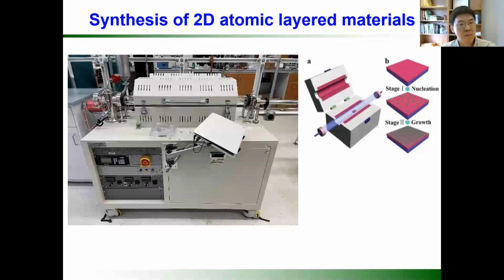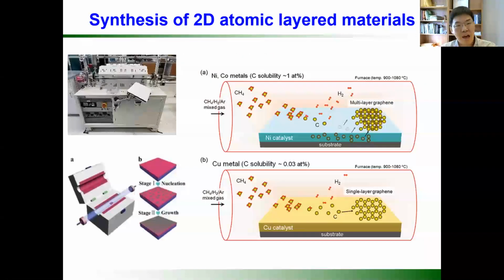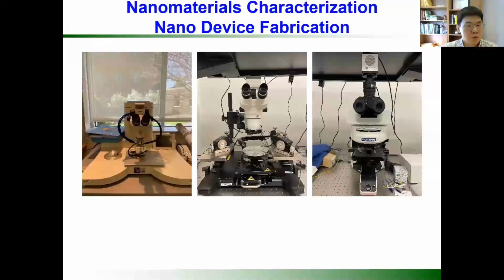At a very high temperature, those methane gases decompose into carbon and hydrogen atoms, and with the copper film, the copper adsorbs only one layer of carbon atoms on its surface. Using the adsorption of just one atom of carbon, we can make a large scale, 5 by 5 centimeter size, film of hexagonally bonded carbon atoms, and that is graphene. So using high temperatures and diffusion of carbon atoms to form these hexagonally bonded structures, we can synthesize large-scale graphene films. And using those, first we characterize how much quality we get.